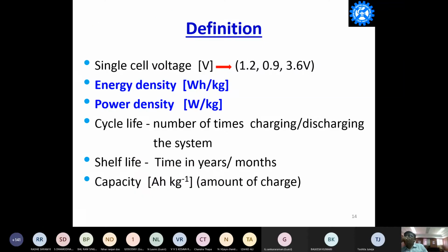So each battery system has its own advantages and disadvantages, and the performance of any battery system is judged by these six parameters. The first one is single cell voltage. If you measure the potential difference of a penlight cell, it varies from 1.2 to 1.5 volts, and some systems show 0.9 volts. If you measure the voltage of a lithium ion battery, it shows 3.6 volts. That is called single cell voltage.